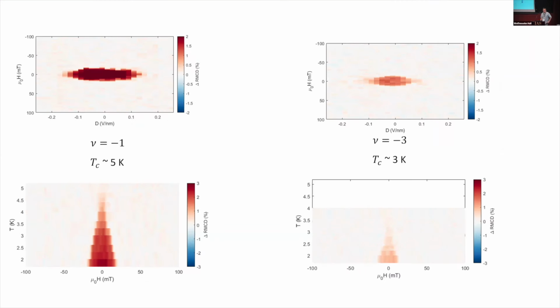We can do a bit more: perform temperature-dependent measurements. On the left-hand side, at the top, is the electric field dependence of this hysteretic component. Everything is consistent: we can use electric field to control the ferromagnetism, and the signal can survive all the way to about 5 kelvins. This is for filling factor -1. For filling factor -3, we can also use electric field to control the ferromagnetism, and again the Curie temperature is about 3 kelvins.